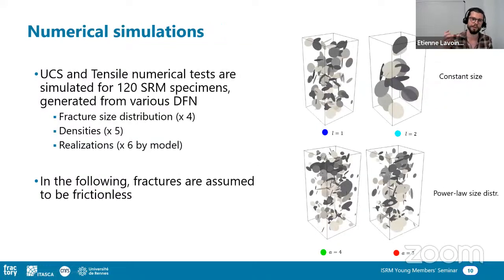So to study that, we covered a wide range of parameters for our DFN analysis. We performed UCS and tensile numerical tests on 120 synthetic rock mass specimens generated from various DFN. So we performed analysis on constant size distribution, where all fractures have the same size, here 2 and 1. And also with power law fracture size distribution with different exponents, meaning that you have more or fewer large fractures than small fractures. In what I will show you, fractures are assumed to be frictionless, so the shear stiffness is equal to 0, because it was easier to start with that, because the displacement on the fracture is more important, so it's easier to analyze everything.